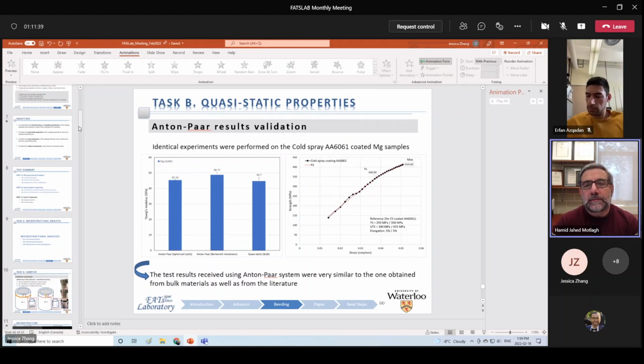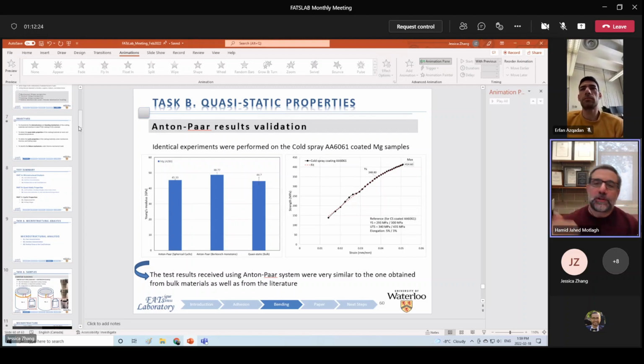So your bend test had the coat under tension, right? Yes. The way you test it, you put the coating on the other side, opposed to where you're applying load. So it would be under tension. So somehow it mimics the bending. Yes. The adhesion test is a pretty standard test. There is an ASTM standard for finding the pull adhesion. It's called pull adhesion. You can also do a scratch test, which is another test of adhesion, in shear mode. Those are for quantifying the strength of bonding, which is irrespective of the actual loading case that you have. It's just a measure of the quality of the bond.